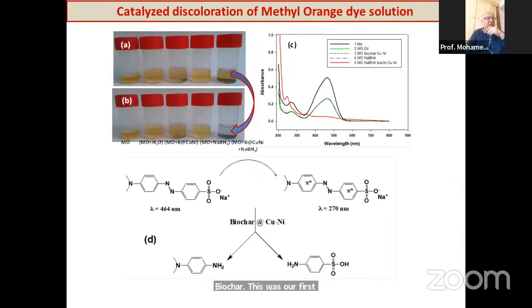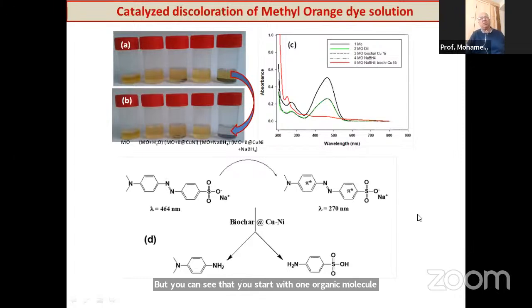This was our first application. It was really at the beginning of our program in early 2021, almost 2 years ago now. We started with something very simple, the degradation of methyl orange, but it was a reductive process. So actually, you can see that with the copper nickel, the molecule is split in two, so you start with one organic molecule and end up with two. So that was our first application to test the concept.